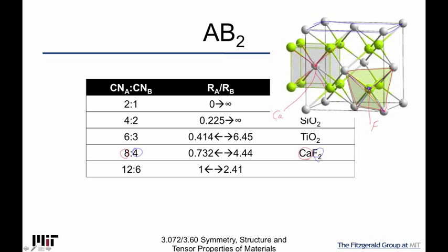So I have 8 of them, 1, 2, 3, 4, 5, 6, 7, 8. Yes, 8 of them inside. And the way you probably remember how you can calculate this is all 8 of those tetrahedral sites are being filled. So I have 8 full fluorine atoms, right?